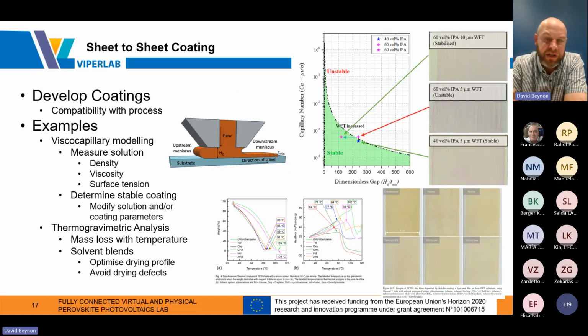And it's at this sheet-to-sheet stage that we do a lot of our development of the coatings before we move on to roll-to-roll. And examples of some of the developments we've done in the inks and coatings is that we will use the viscocapillary model to ensure that we can get a good and stable coating regime. So we will measure the solutions, so we can take the density, viscosity, surface tension, all facilities we have available, measure those properties of the solution, and use the viscocapillary model to determine whether our coating will be stable.